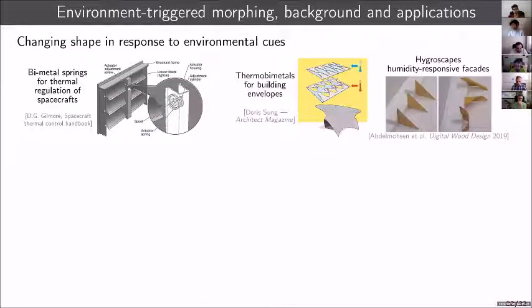The idea of morphing systems in response to temperature is actually very old. Here I have an example of a technology that's quite used in spacecraft. These are louver systems. Louvers are these things that open and close, and they're connected in this case to a bimetal spring. It's made of two different metals on top of each other that have different coefficients of thermal expansion. So when the temperature increases, one of the two materials expands more than the other, and the spring unravels. When the spring unravels, the louvers open and they let the heat inside the spacecraft radiate out. So it's quite an old idea.